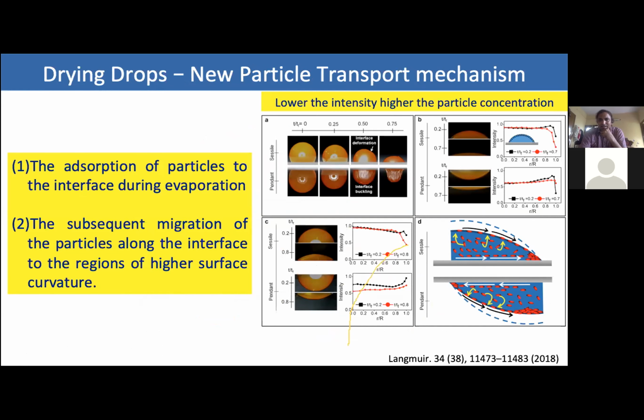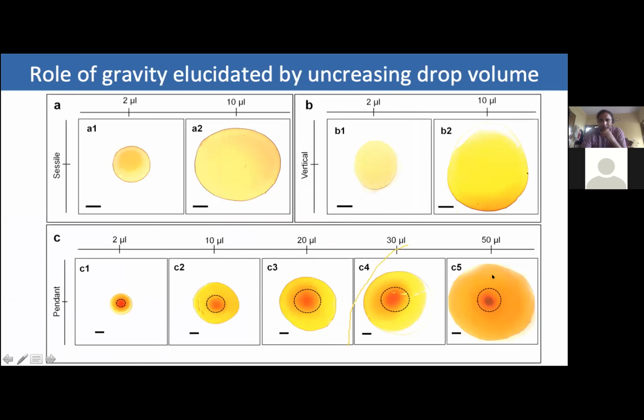Okay, and for this, the adsorption of the particle at the interface is important, and that is known to occur because the interface anyway recedes during evaporation, and this receding interface captures some particles, and once the particles are at the interface, they can move along the interface as well, leading to the coffee ring formation or the central dome deposit formation. And this occurs independent of the drop volume.